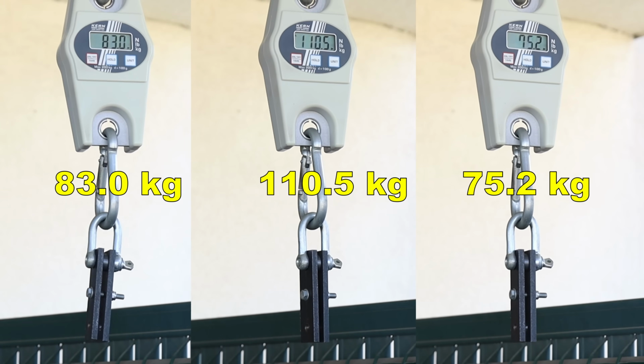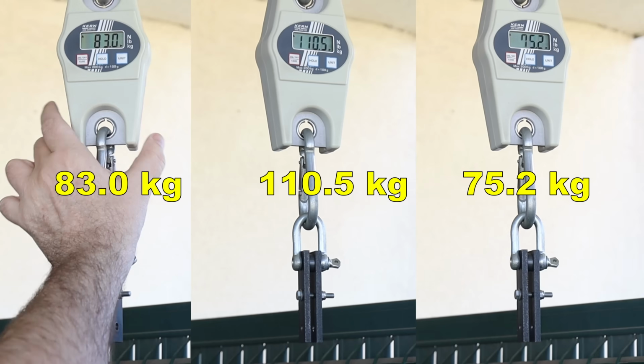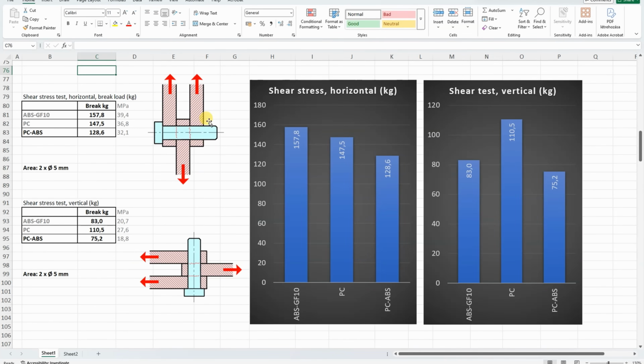Shear test, side-by-side, horizontal printed objects. Shear test, these are printed in vertical position. Printed in horizontal position, fibers always help here, and of course ABS-GF is the strongest, but not much weaker is the polycarbonate, and a little bit lower the PC ABS. Printed in vertical position, layer adhesion is very important, and no surprises here, the PC is the strongest.